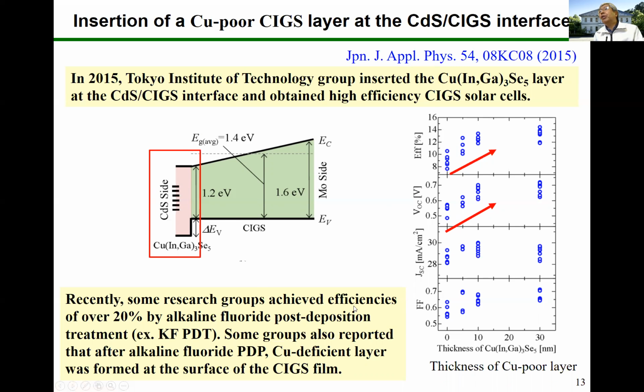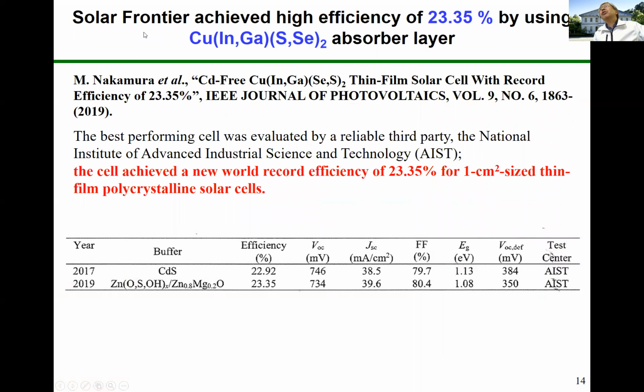Recently, some research groups achieved efficiency of over 20% with alkaline fluoride post-deposition treatment. Some groups also reported that after alkaline fluoride post-deposition treatment, a Cu-deficient layer was formed at the surface of the CIGS film. Solar Frontier achieved a high efficiency of 23.35% by using a Cu(In,Ga)(S,Se)2 absorber layer.